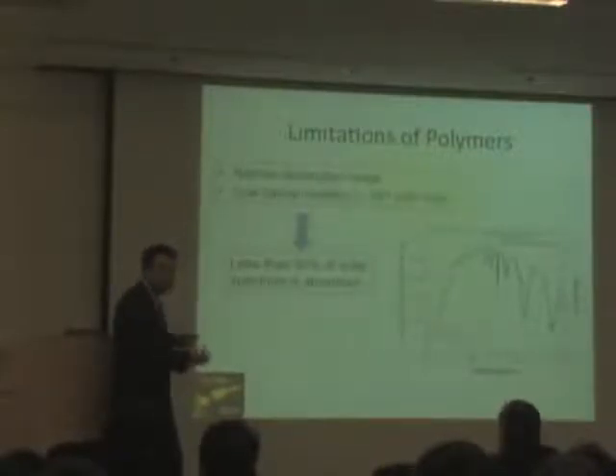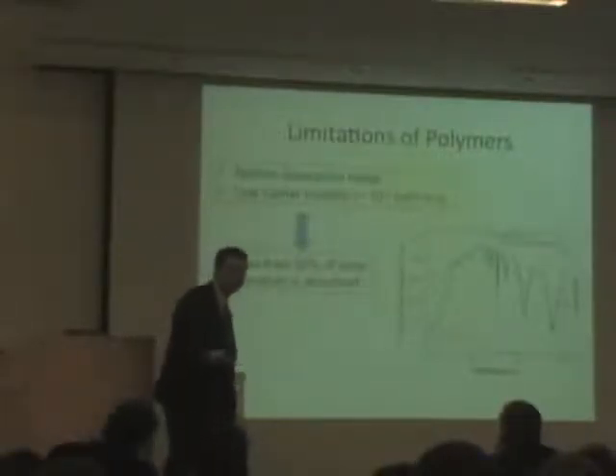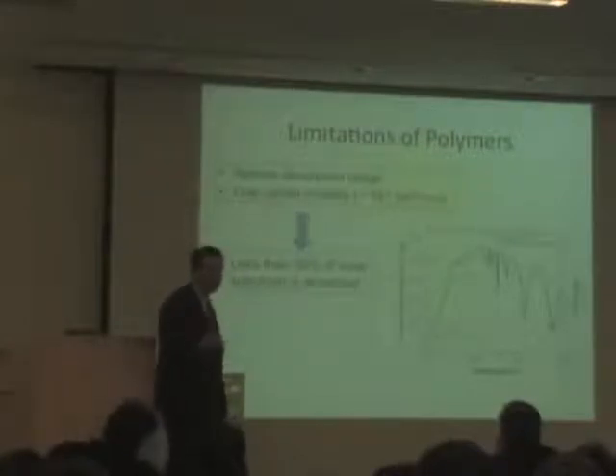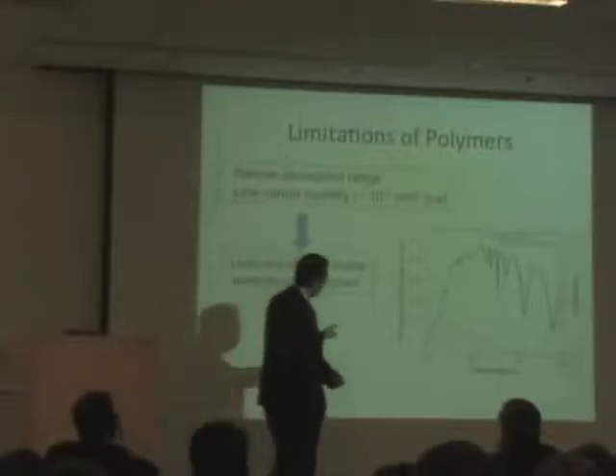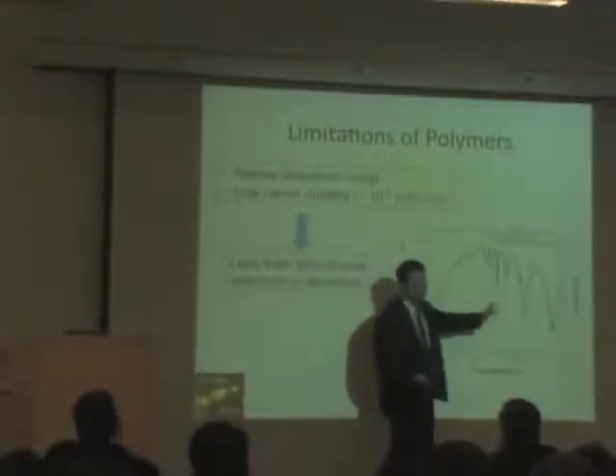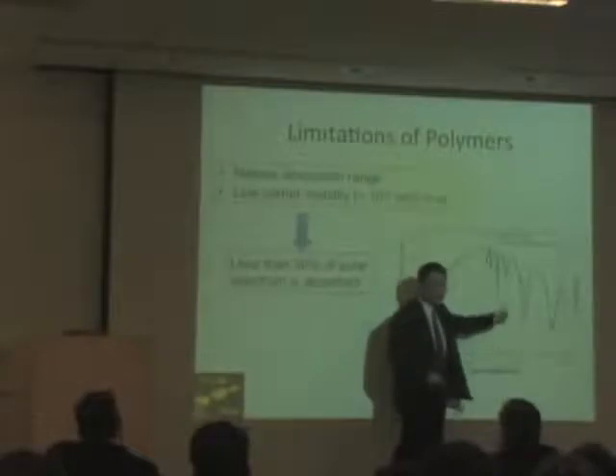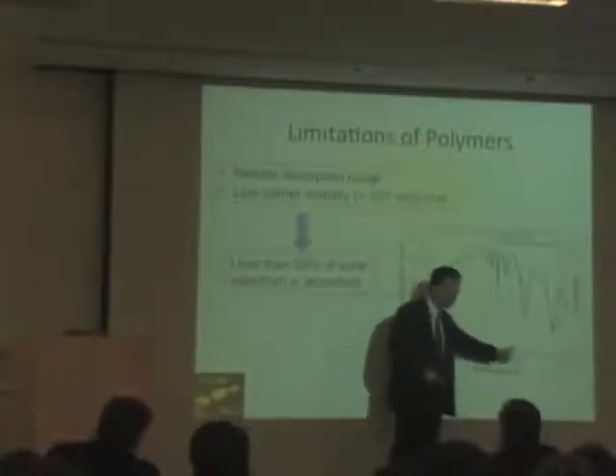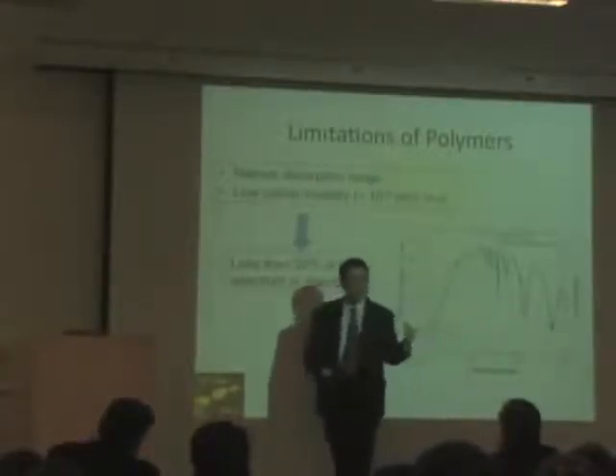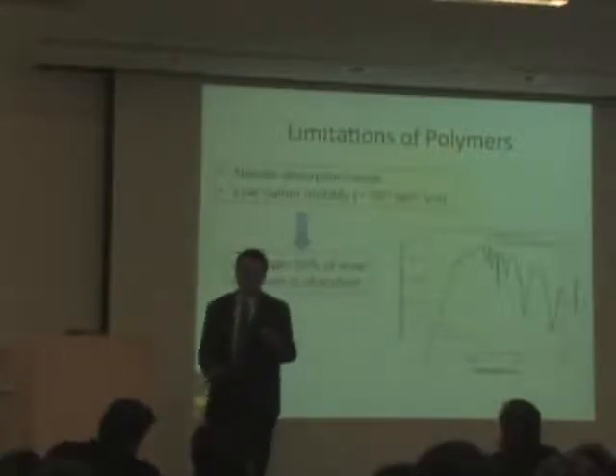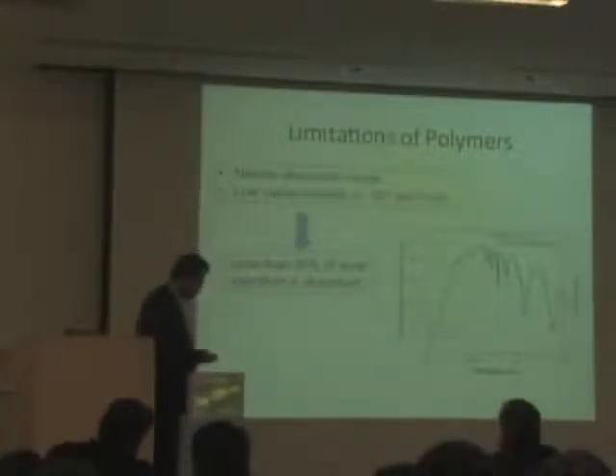And the other possibility is, okay, how about we mix two materials together? But the problem with that is VOC. If you remember the equation of the efficiency, it's not just current; open circuit voltage also plays a role. So one can move this absorption more into the infrared. But here's what we call the bandgap. Your open circuit voltage will be subject to the bandgap. The smaller the bandgap you have, the smaller the open circuit voltage you have. And then the absorption will not necessarily help you that much.